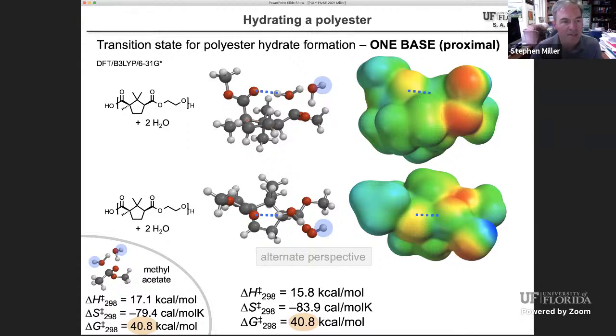Now, this has maybe an advantage of being built from camphor. Camphor is, stereochemically, a cis diester, a diacid formed into a diester here. So maybe it's particularly easy, because of that stereochemistry, to bring that carbonyl group up close to this water molecule. But bringing just one of them, what does it do? Well, you don't really change the enthalpy that much. It's about similar enthalpy, maybe a slight decrease in the enthalpy penalty, more enthalpically favorable. The barrier goes down by 2 kcal per mole, but because you have some conformational restriction in this transition state, you pay a small penalty for the entropy. Altogether, you get about the same barrier when you approach this transition state with a single nearby ester group.